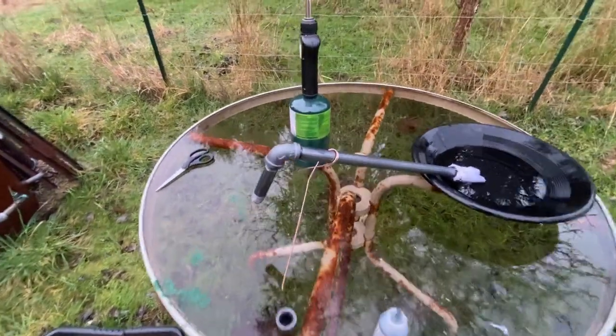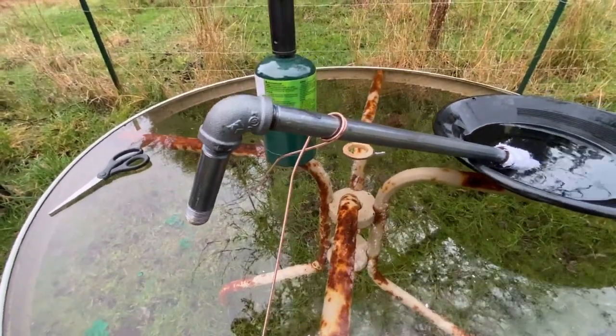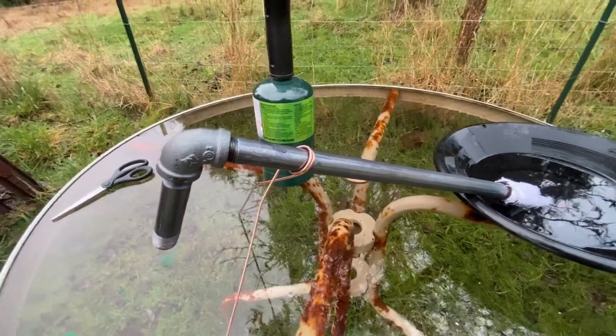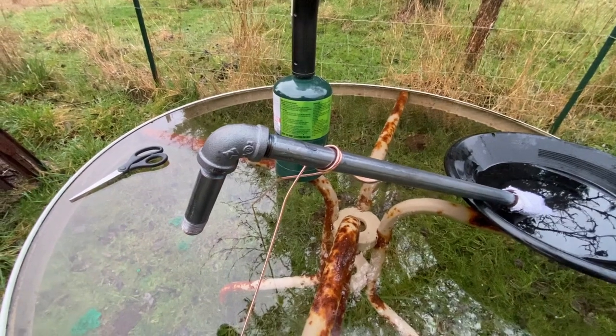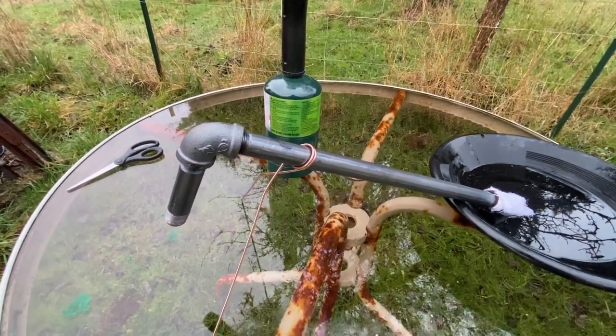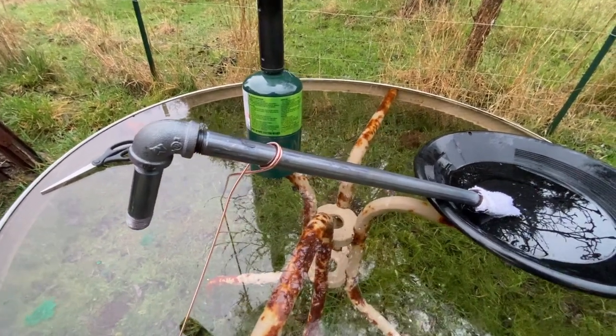What I've done is I've just gone down to the local hardware store and bought some black iron pipe. I've cleaned the black coating off of it with acetone. There's no galvanizing in this — you don't want galvanizing because of the zinc they use. The mercury will stick to that galvanizing, it'll amalgamate a little bit to the zinc.